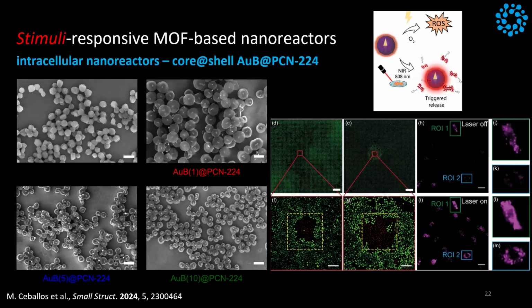And as we did before, you can imagine for this MOF, we have a bipyramid that has a lot of interesting properties in the near-infrared light, and we have the porphyrin. So we could use two excitation sources, a green laser, a red laser also works, and a near-infrared one. The green one is for exciting the Soret band of the porphyrin to create ROS and kill the cells. This is not very interesting, but you see here what happens. This is, if I'm not mistaken, a scan of 100 images of the cell. You see a lot of squares, and then we only excite the porphyrin here, and when we excite it, we kill the cells by generating reactive oxygen species from the porphyrin excited in the Soret band.